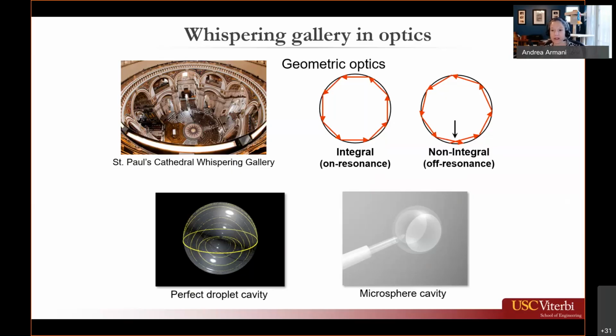The first whispering gallery mode resonators in optics were actually perfectly spherical suspended droplets in vacuum, and they were suspended based on the optical trap. So it was basically a liquid droplet being held by an optical tweezer. Light was coupled into it using a free space laser. So these were very delicate experiments. More advanced experiments quickly followed using silica microspheres and crystalline microspheres, which provided a much more stable platform to perform more advanced experiments. One example is shown here.